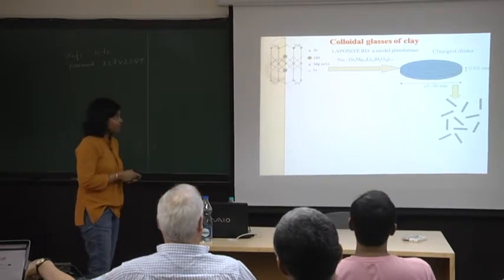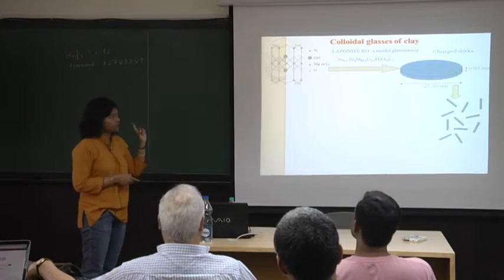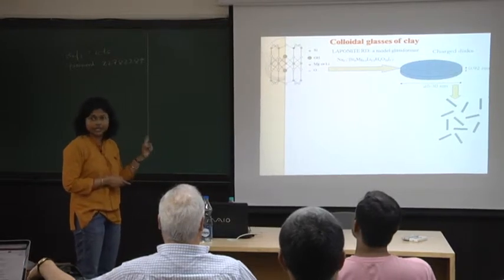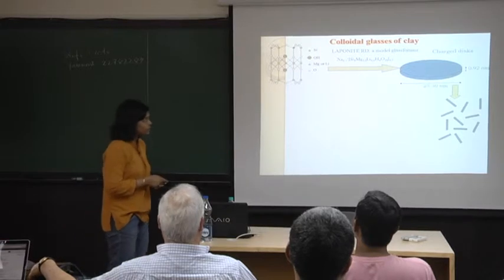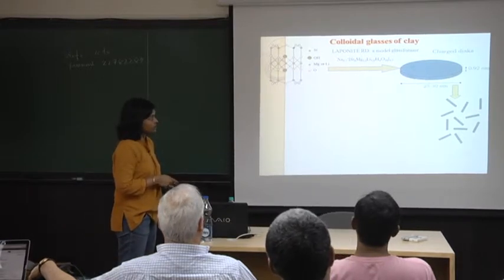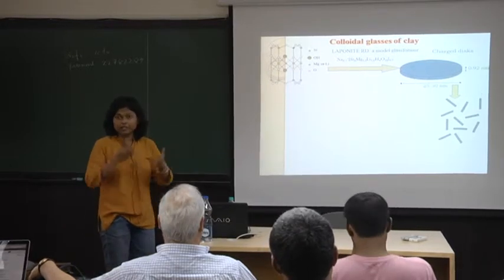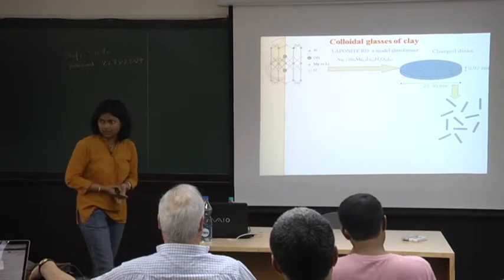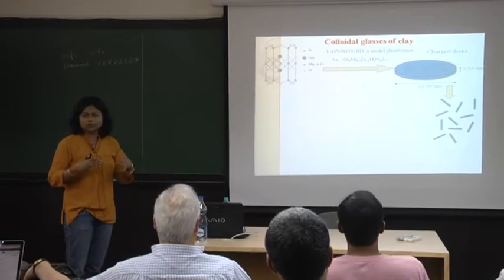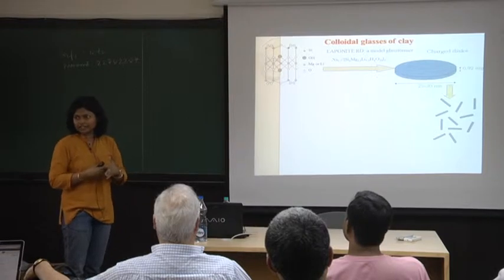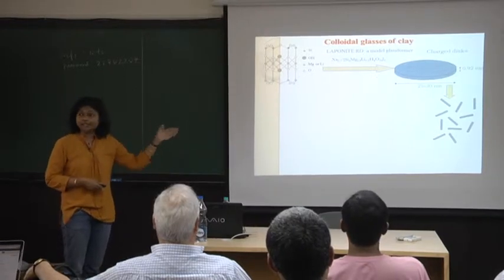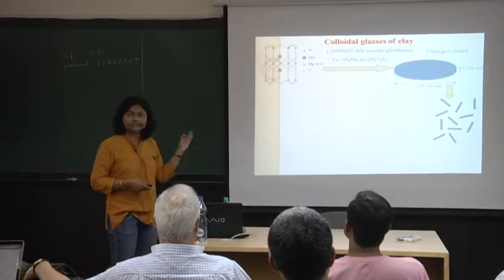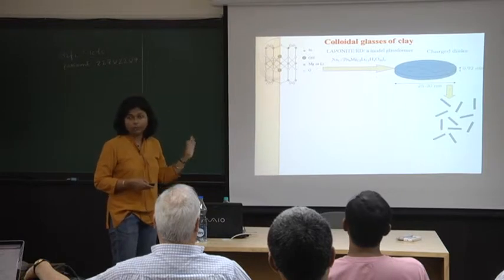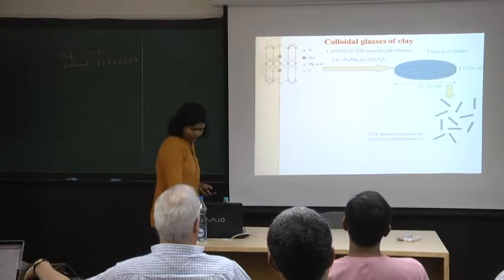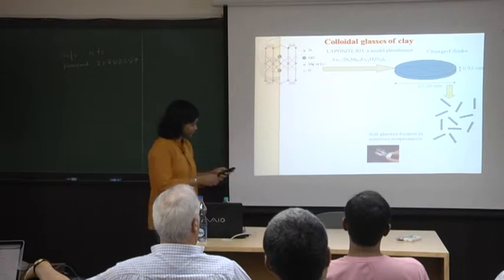But remember that the excluded volume fraction here is rather tiny because each disk is surrounded by a large Debye cloud, and these are all positively charged clouds, so they all repel. They don't really want to get too close together. So this is a system that ends up being kinetically constrained at very low volume fractions, like 1%. So you can form a soft glass in suspension.